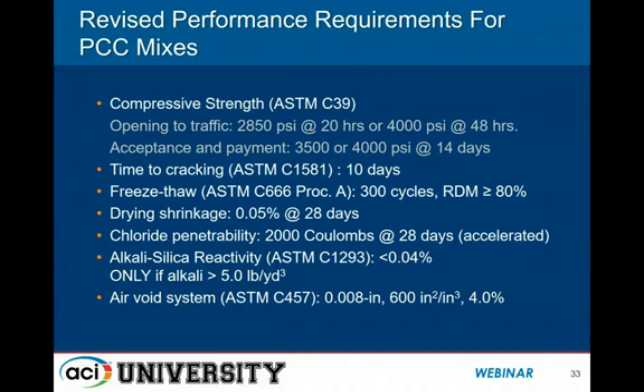The time to cracking minimum for a patching material in this system is considered 10 days. So we have basically the bare minimum that we need to make a small patch in a deck or a pavement and not see cracks. With respect to freeze-thaw, we have a performance test requirement there, and also for drying shrinkage. And these are more for our long-term durability, so we're trying to emphasize that as well.